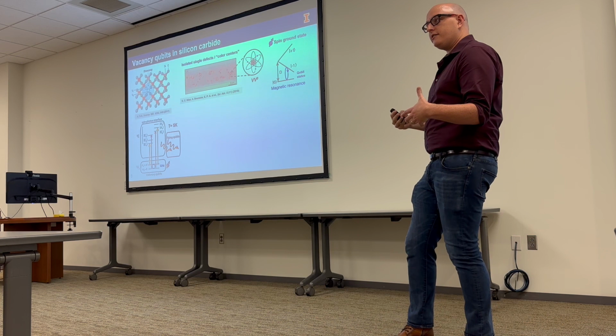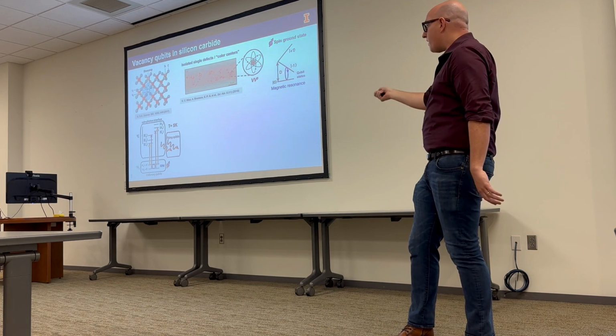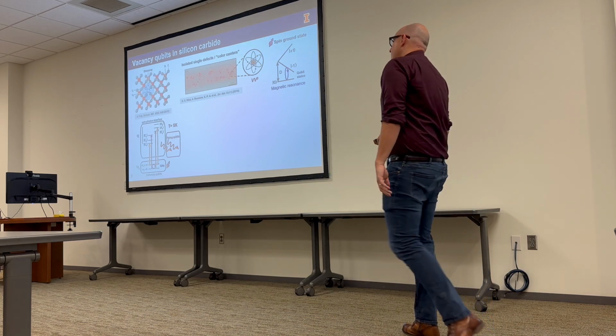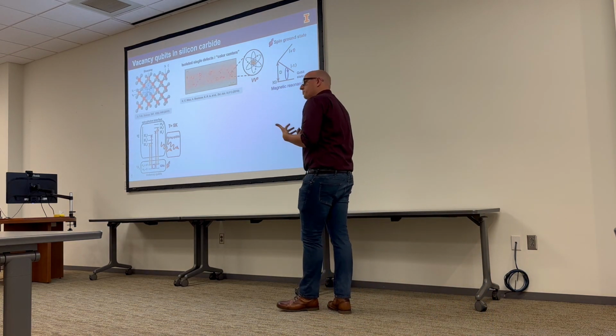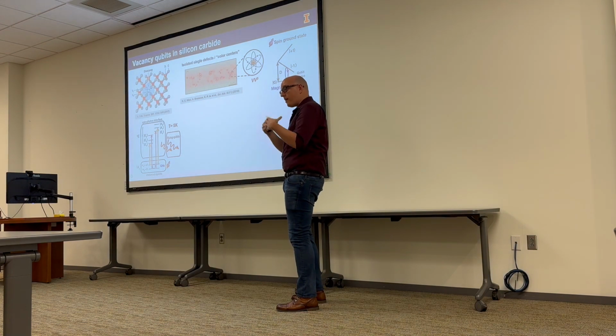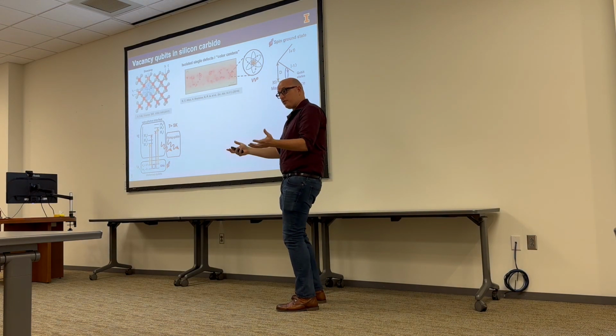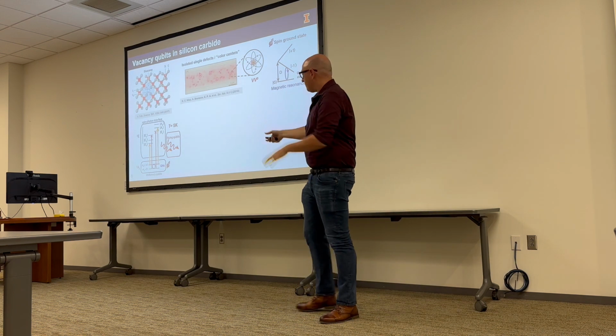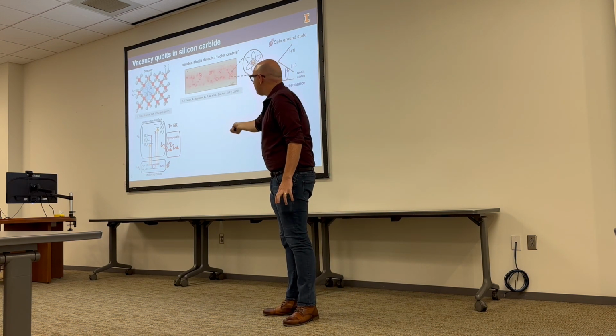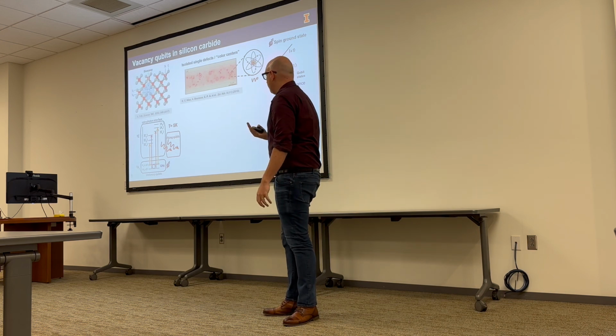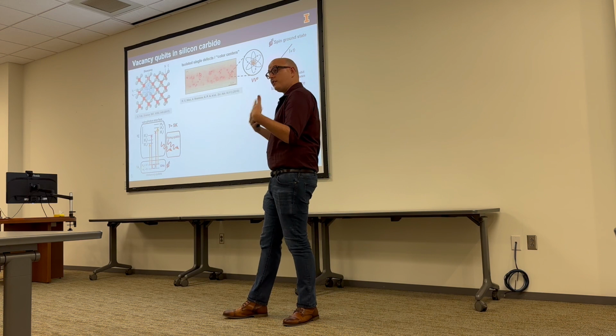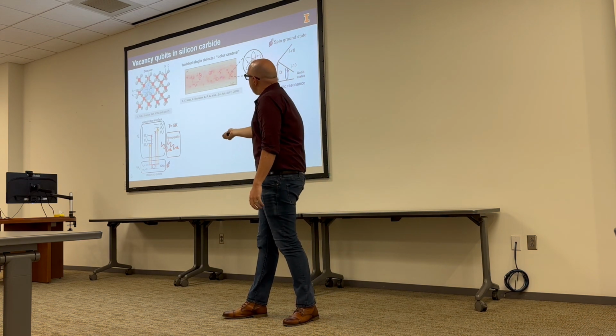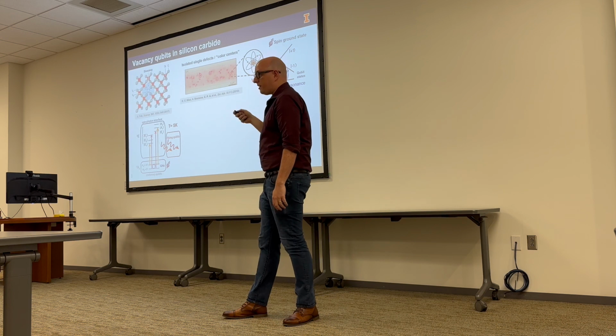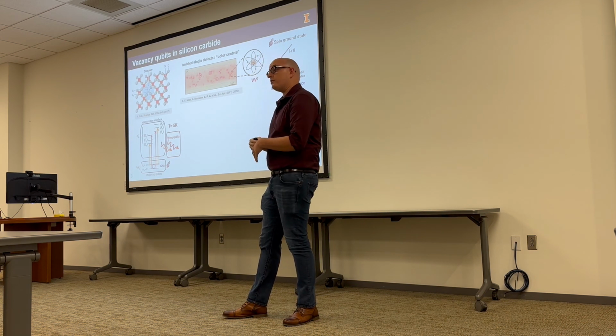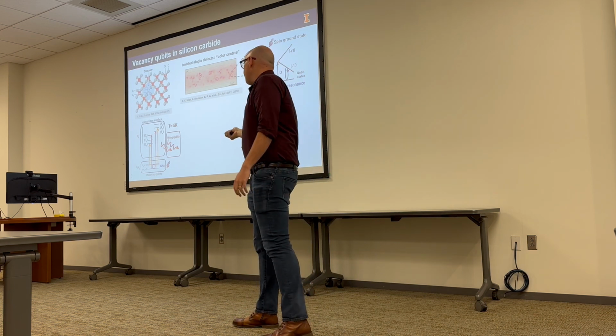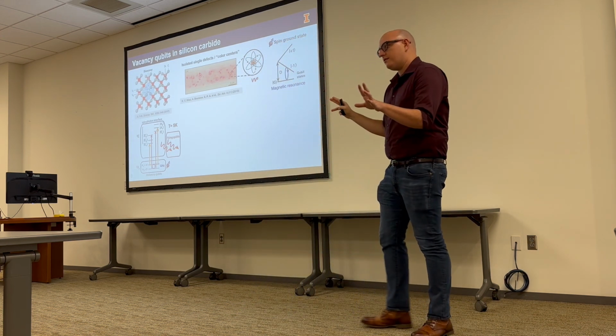So I keep saying the system looks like a trapped atom. We have a spin ground state, but we also have these orbital excited states. If we cool the system down to low temperatures, these orbital states resolve. Once again, like a trapped atom. You have your hydrogen, there's selection rules, there's optical transitions, there's hyperfine states. Same physics here, where we have our three ground states, and then we have these excited state orbitals that we can address with narrow line lasers. And once again, in analogy to atomic physics, there's selection rules. And it turns out that for this system, certain ground states couple to certain orbital excited states, and other spin ground states couple to a totally different set of orbital excited states. And those are separated in frequency, and they're resolved.